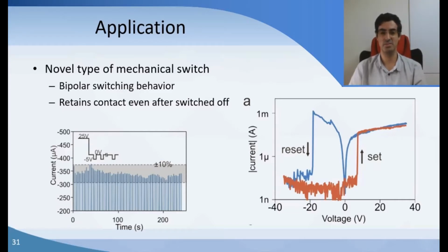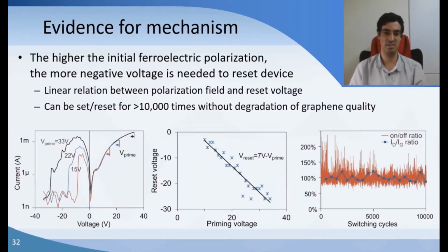It's not only distinguishing between on and off, because now ferroelectrics and mechanics are working together. You're getting memristive behavior. Basically, your performance depends on history, like a memristor. In our case, it means that the voltage at which reset occurs depends on the previous highest voltage that we used to initialize the ferroelectric. And it's very linear over a very large range, so you can use that as a multi-bit memory. It's also very reliable and very quick. We can switch it thousands of times without deteriorating its performance or the quality of the graphene.